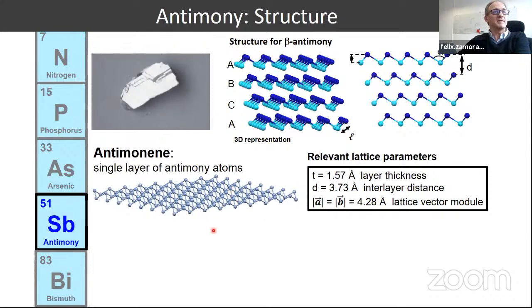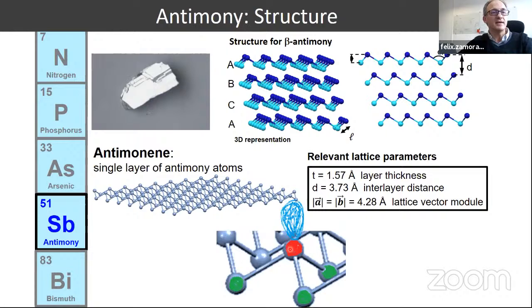Okay, so let me just very briefly summarize the structure of beta antimony, because we will use some of these parameters later. This is the structure of the beta antimony bulk crystal. Here you can see that it's formed by layers with this thick disposition of the atoms into the layer, and every single atom is connected to three other antimony atoms along this layer. Here, I gave you some relevant lattice parameters that we will use later for the material characterization.